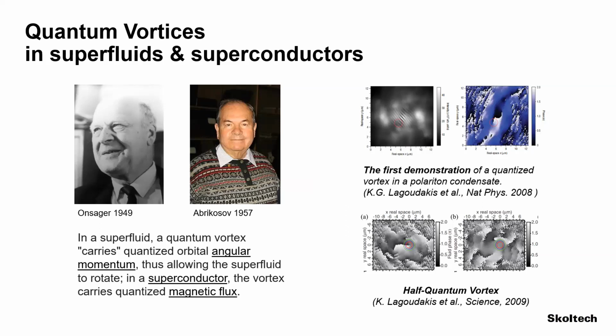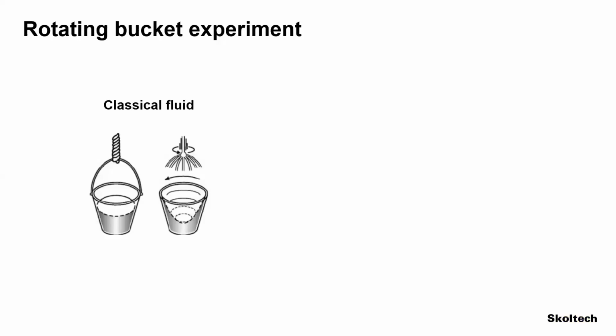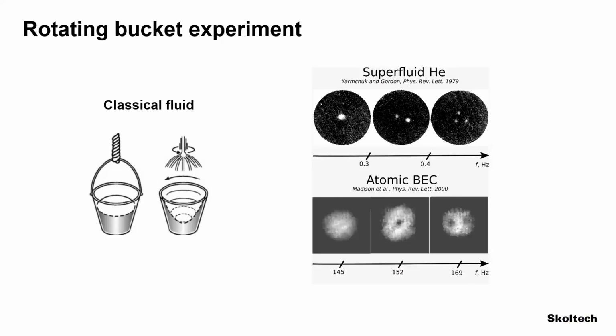However, in a superfluid, you get quantum vortices forming when you do the rotating bucket experiment. That's a beautiful experiment where if I have a classical fluid and I put it in a bucket and I spin the bucket around, the classical fluid goes against the walls. Do the same thing with the superfluid, and what you get is a flat surface and vortices forming inside the superfluid. The first experiments back in 1979 showed that as you increase the speed of rotation, you get formation of quantum vortices in helium superfluid.